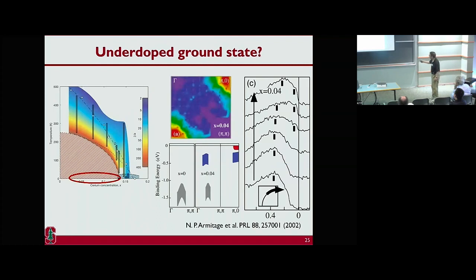In fact, it's already sort of hinted in Peter's thesis. I don't know whether you remembered. Looking back, those features are still gapped, but we didn't pursue that. That's again the Fermi surface like feature near the antinode. That's what we are trying to do. The gap I'm talking about is very different from the antiferromagnetic Mott gap. At half filling, the energy scale is much bigger. So already, even at 4%, there's a lot of low-lying excitations near the antinode.